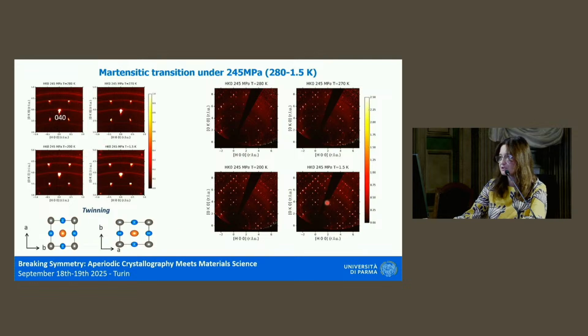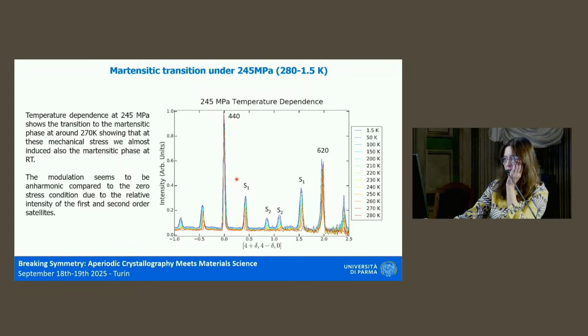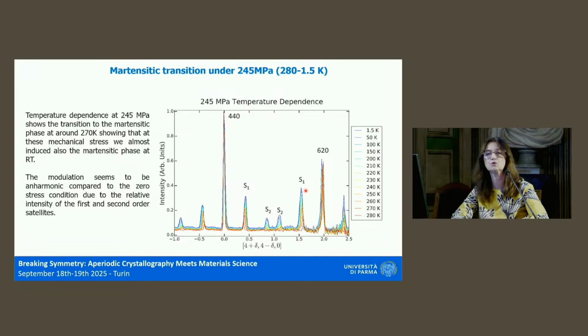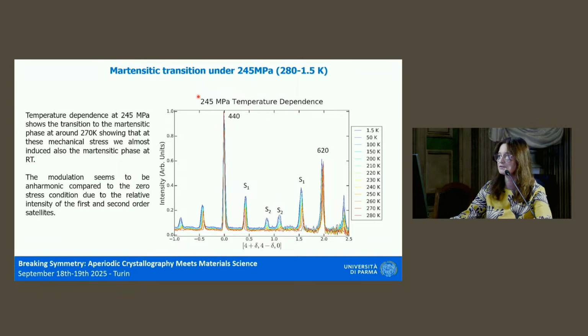And by going down with the temperature, we can see that the intensity of the satellites grows. So by looking at the evolution of the intensity of the satellites with respect to the intensity of the main reflection, so we are now observing a single row of spots, we can see that the intensity of satellites grows as the temperature is going down under 245 megapascal of uniaxial compression. So our interpretation of this is that probably under these conditions, the modulation is not harmonic, is not a wave-like type of distortion, but looks like an anharmonic type of modulation with a discontinuous modulation function.